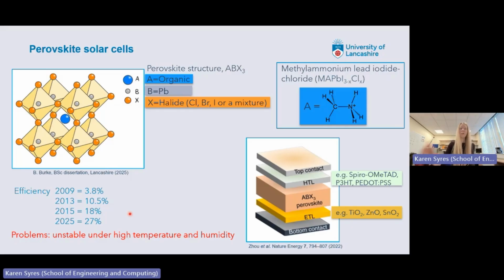efficient. So the efficiencies are going up massively, but we still can't commercialize them because they are still very unstable. The problem is that the perovskite degrades very quickly. It's unstable under high temperature and humidity, which isn't ideal when you're planning to put these things outside where they're likely to get hot and humid. Obviously there needs to be more work on these to stabilize them before they can be commercialized.